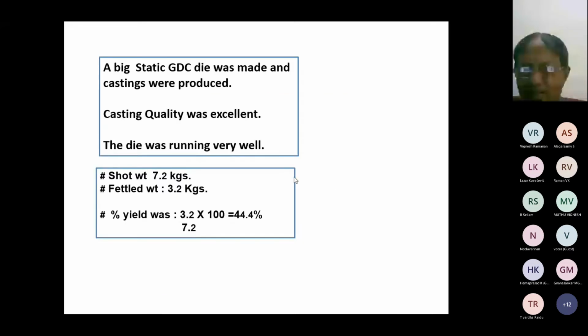Now, a big static GDC was made to produce these castings. And the casting quality was excellent. The die was running very well. And the yield was only 44.4%, which is very low.